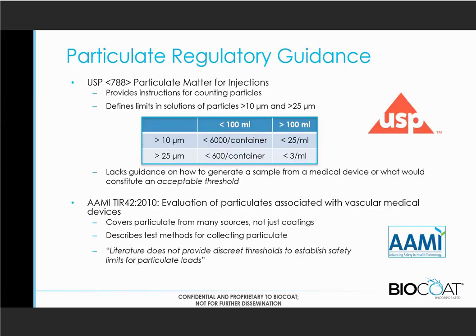So what do I mean by this? Let's give a few examples here of some of these regulatory guidances. Probably the most well-known is USP 788, which is particulate matter for injections. And it does a very good job of providing instructions for counting the particles once you have your vial of particulates suspended in a solution. And in fact, it defines limits for those particles in two sizes, greater than 10 microns, as well as greater than 25 microns.